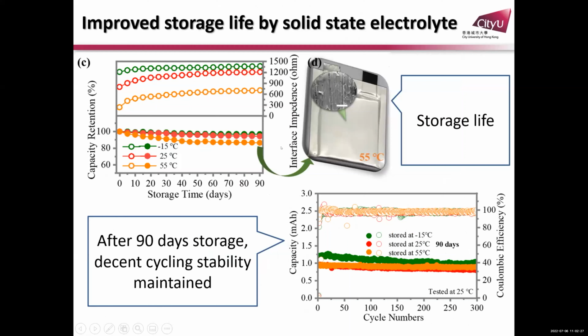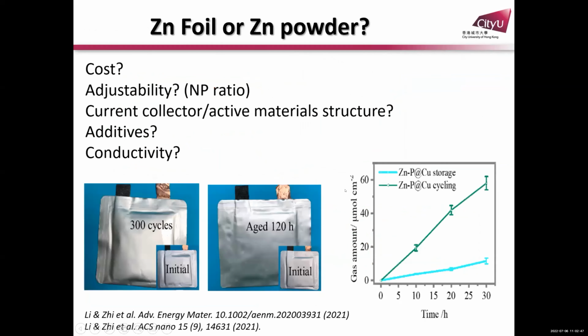If you change to solid state electrolyte, within 90 days the stability is quite good. Again, I have to mention that we sacrifice the kinetics with solid state electrolytes, so generally you cannot have very good rate capability.